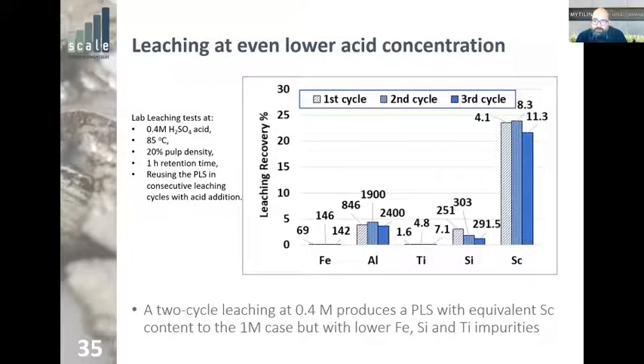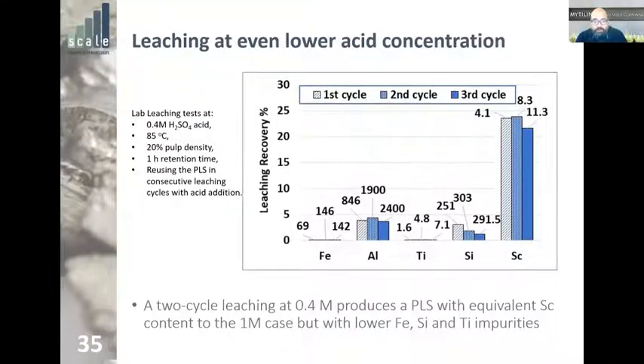So as you can see here, this allows us to get in 2 steps all the way up to 8.3% of scandium, while iron and titanium remain relatively low. Even a third cycle could be used, but in the third cycle, you see, we start losing in leaching recovery of scandium, so it doesn't seem to be needed. So this was the third campaign of two leaching cycles to get a relatively high scandium pregnant liquid solution with low iron and titanium.